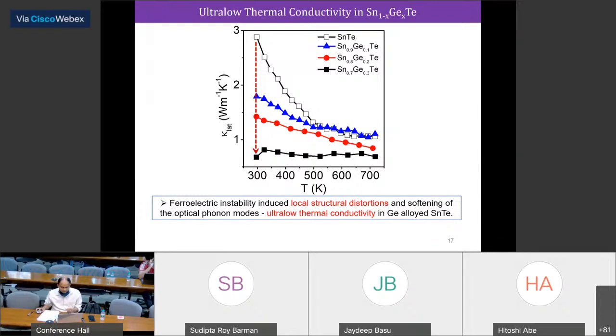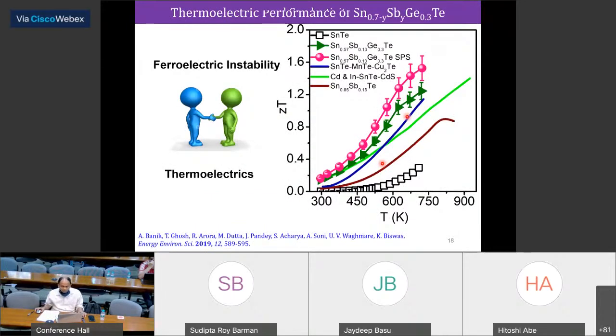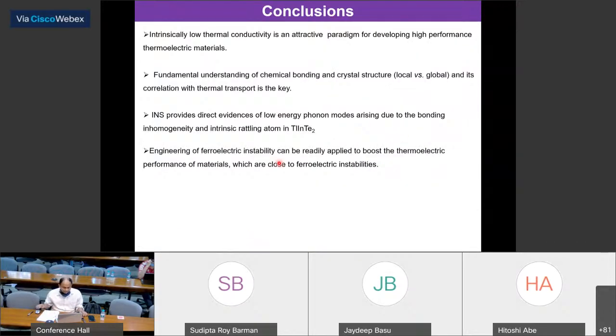You can see there is a huge decrease when you dope germanium at 30 percent in this tin telluride. And with that, we got a very, very high ZT, around 1.6 in this material. So this paper actually shows for the first time that these two fields, ferroelectric instability and thermoelectrics, can couple for good reason and give rise to high thermoelectric performance. And this work is published in Energy and Environmental Science in 2019. With that, I'll conclude the talk.